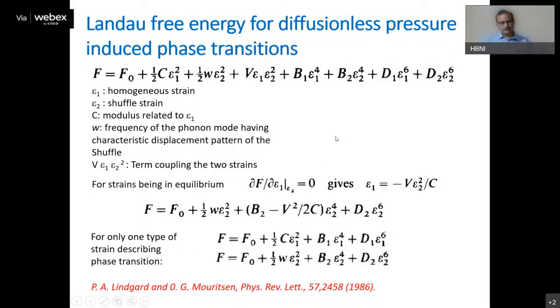Okay, now let us discuss the Landau free energy corresponding to these strains that I discussed earlier. This analysis was given by Lindgård in this paper, and he expressed this Landau free energy as a power series of both kinds of strains. Your epsilon 1 is the homogeneous strain and your epsilon 2 is the shuffle strain. You have higher order terms from both the homogeneous strain and the shuffle strain, and then there is a term which corresponds to the coupling between these two strains. Based on this expression, we can try to understand different classes of phase transitions based on the symmetry.